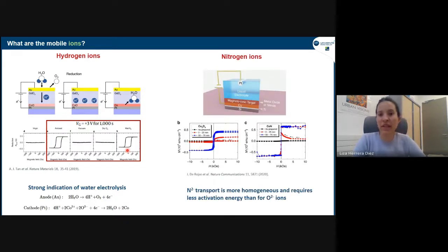And it has been shown as well that nitrogen ions can be used for magneto-ionics. This is an approach that is more on the electrochemistry side that I showed you at the beginning. Here they grow the magnetic film in situ, and with cobalt oxide they can really oxidize it fully and then recover it fully, recovering cobalt in the ferromagnetic state. So they can go back and forth very nicely from a complete metallic state to complete oxidation. And they can do this as well with cobalt nitride, getting also a very nice response between the fully metallic cobalt and the full cobalt nitride.